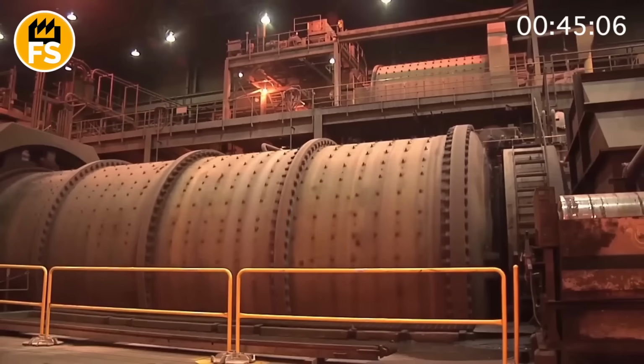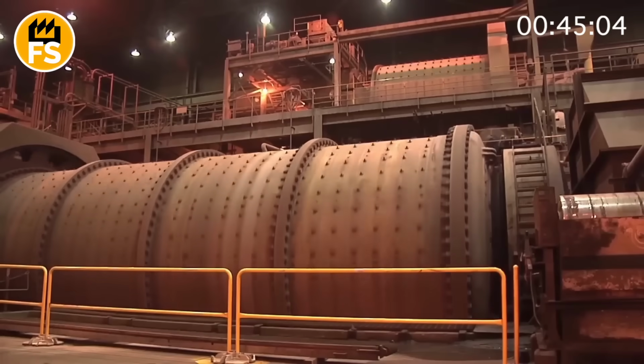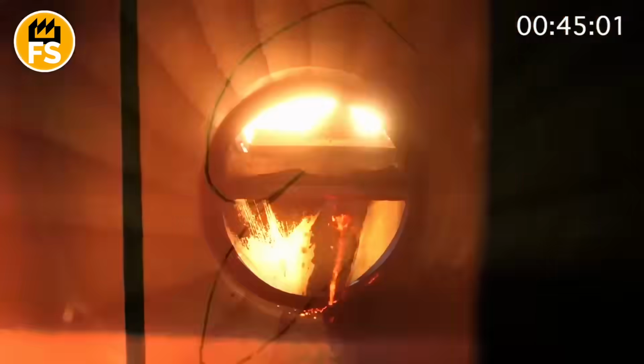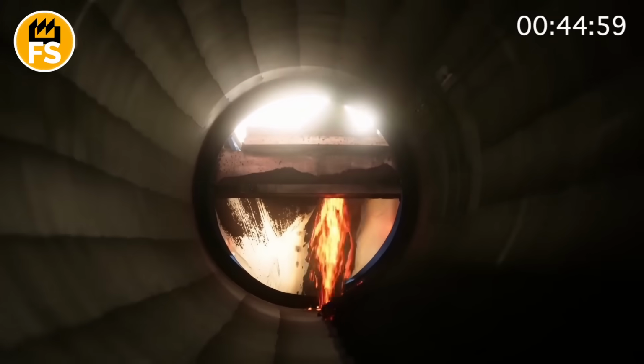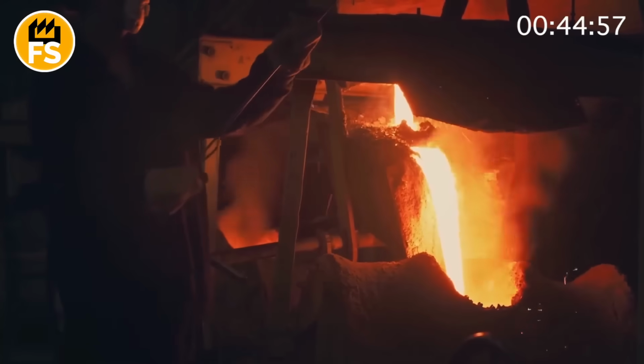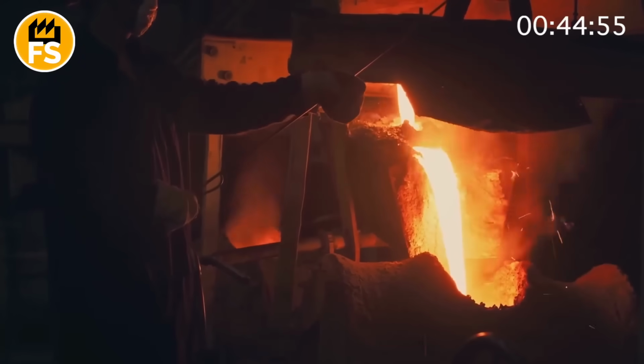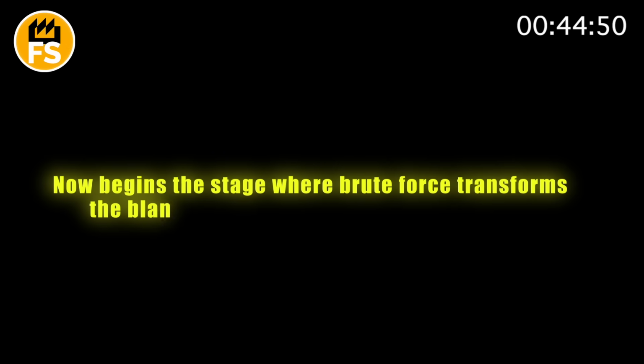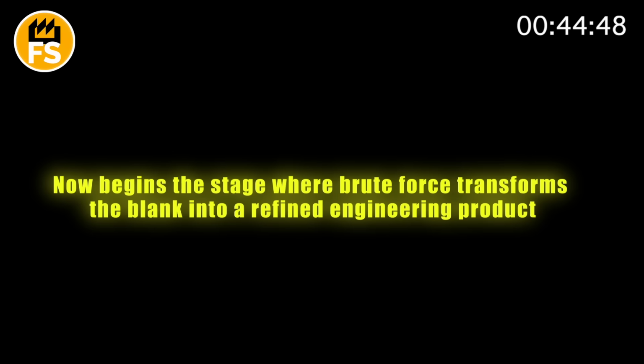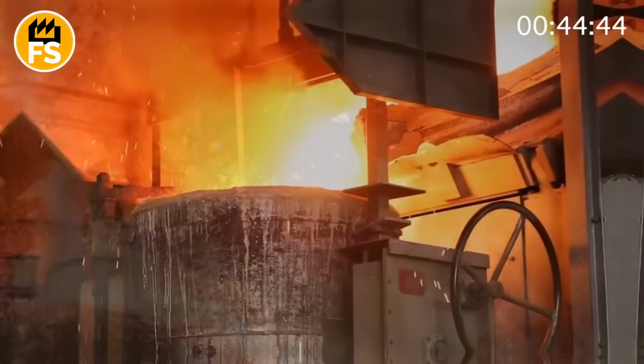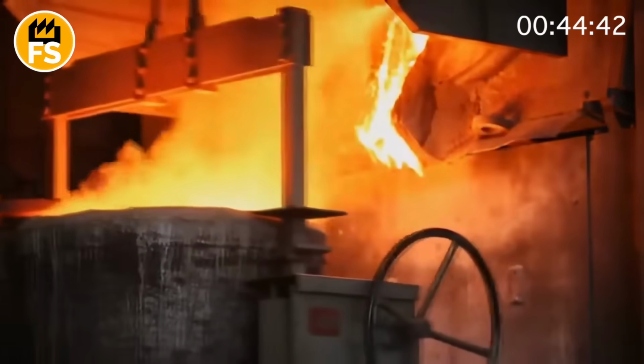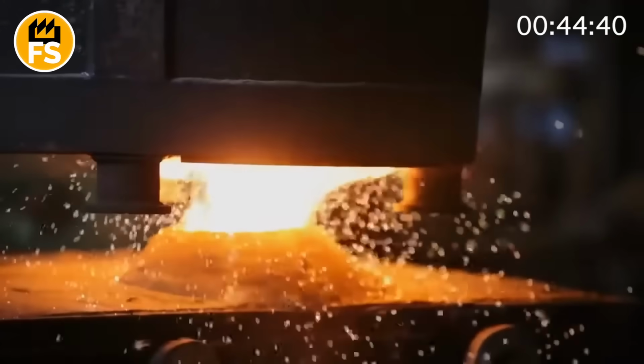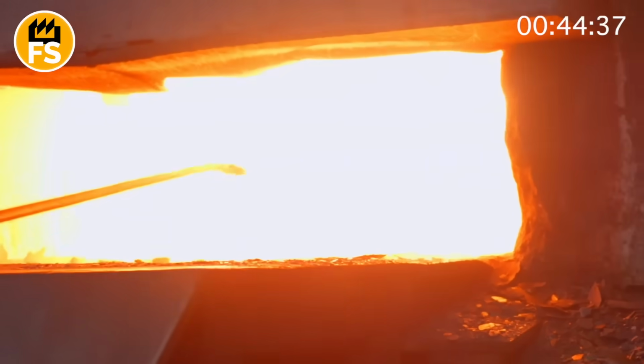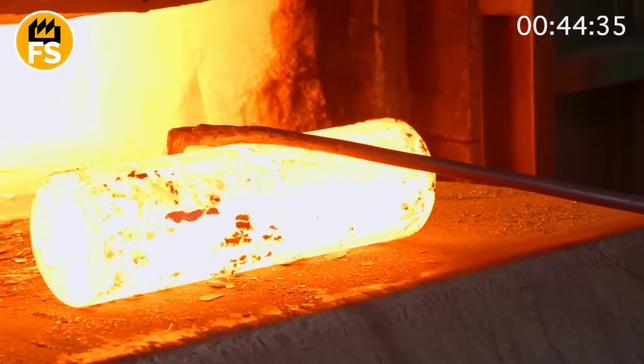For about 20 minutes, the steel solidifies, and the hot, still red cylindrical blocks, called blanks, are extracted from the molds. This is just a rough hint of the future wheel. Now begins the stage where brute force transforms the blank into a refined engineering product. The blank is heated again in a furnace to a plastic state, approximately to 2,250 degrees Fahrenheit, and sent under a press. This is a hydraulic machine with a force of 4,000 tons.